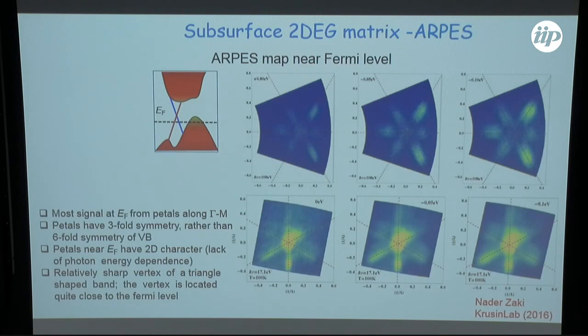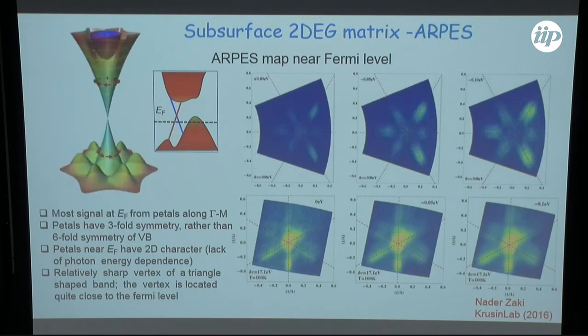And yes, indeed, this is Nader's ARPES data, where he actually probed subsurface states by changing the energy of photons in ARPES. Two things he found. One is that the subsurface states have threefold symmetry rather than the sixfold symmetry of the valence band. This is just a cartoon.